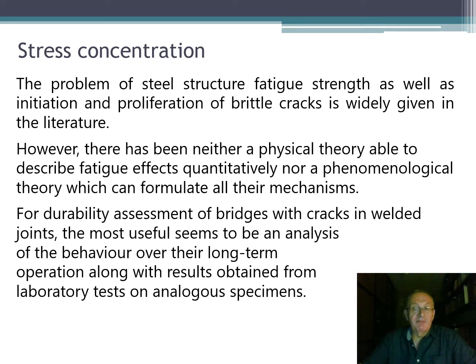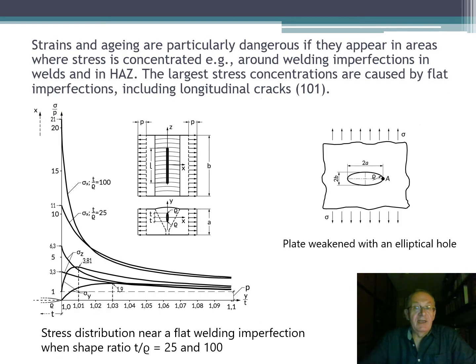For durability assessment of bridges with cracks in welded joints, the most useful seems to be an analysis of the behavior in long-term operation along with results obtained from laboratory tests of analogous specimens. Strains and aging are particularly dangerous if they appear in areas where stress is concentrated, that is, around a welding imperfection, in welds and heat-affected zones. The largest stress concentrations are caused by flat imperfections, including longitudinal cracks. So the concentration of stresses is very large, and the theory of notch stresses should be applied.